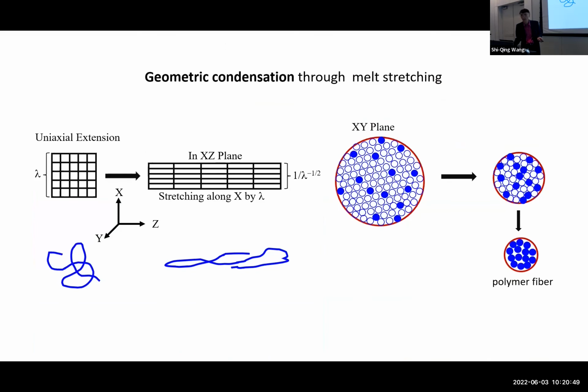And for me, this allows me to introduce a concept which I kind of own, because it's a concept that's well known, supposedly. Basically, there's geometric condensation of the chain network. So if I stretch in the Z direction, and then I look head on, I find my load-bearing strands condense. It's the same cross-section area that's shrinking, but I still have the same number of load-bearing strands. And in fact, the limit of that is fiber. This is why fiber is strong, because every area is effectively bearing the load. In other words, prior to that, this network is very sparse, it's very loose.